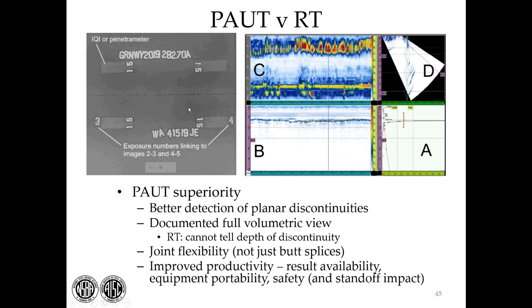If you had something that was a very thin discontinuity like a crack, you might not see that with an RT, especially if that crack is in that same plane as the RT, for example, looking down on that weld. Whereas with phased array, because you're coming at it at various angles, you're sure to catch that. So much better for planar discontinuities. It gives you that full volumetric view documentation, as you see.